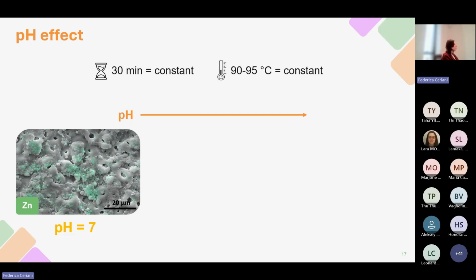In this case, we could note that just a few zinc precipitates are present on the oxide surface, and moreover, the porosity is almost completely unaltered with respect to the one of the original PEO coating. So working at this pH, the sealing process is quite unsuccessful.